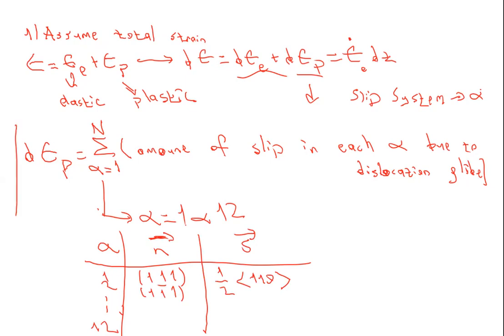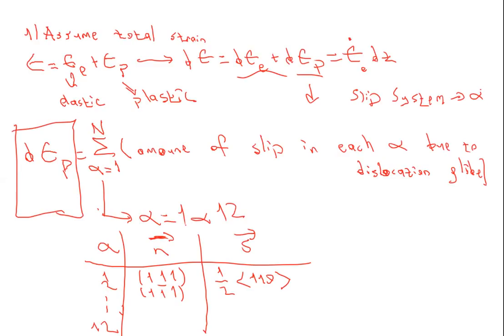Then we have the definition of plastic strain. And if you remember the Orowan equation, we can calculate the shear rate by the Orowan equation. And without going into the Orowan equation, maybe we can go one step forward and define what this is in terms of a formula. So dε^p is equal to the sum from alpha equal to 1 to n, whatever it is, of the amount of slip in each slip system, which corresponds to the shear rate, gamma dot, for each slip system.